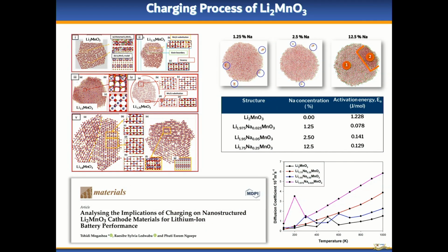Before we move on to the main business of the day, I just wanted to show that we've attempted elemental doping. This was a PhD study by Dr. Morashwa. What she did first was the charging process of the pure Li2MnO3 cathode material. And during this, she was able to demonstrate that there is indeed a layer to spinel transformation. To try and remedy this, she used sodium as a dopant. Because sodium has a larger radius, it's able to enhance the interlayer spacing. It increases the spacing such that the bonds between the manganese and the oxygens are much stronger, and the manganese do not migrate to the lithium sites.